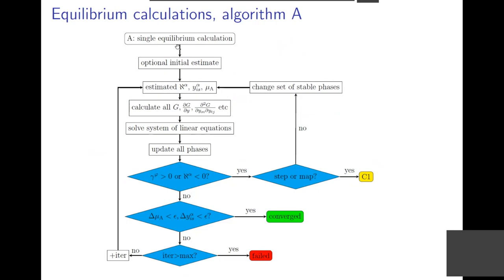We published a paper last year where we tried to explain how OpenCalphad works in calculating equilibria and phase diagrams. And this is the kind of figure where you try to explain what happens. So you have to specify conditions for your system. You have to guess an initial set of stable phases and their compositions. And in OpenCalphad, there is a grid minimizer which obtains this. And that gives you an estimation for the amount of phases, their compositions, and the chemical potentials. Then one has this Lagrangian multiplier equation, where you calculate all the partial derivatives. You have a linear system you solve, and then you update the composition of all phases.